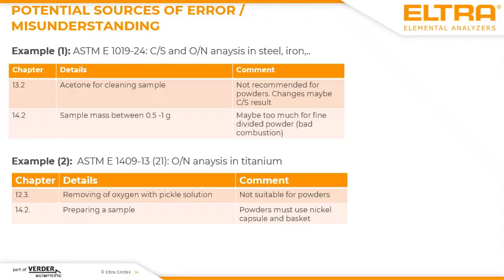And these are, for example, possible conflicts you are facing with your analysis when you are not familiar with powder analysis in the first round. When you have a look at the very prominent standard ASTM E1019, which mainly deals with CS and ON analysis in steel and iron-based samples, you would find just a statement in one chapter that it's okay to clean the sample with acetone. But this is something you should not do when you have a powder-based sample, because then you have maybe some chemical reaction effects or some absorption effects which should be avoided. The other thing is the applicable sample mass. You find in one chapter a statement that you should apply a sample weight between 0.5 and 1 gram. But this sample amount could be too much when you have a very finely divided powder, which is blown inside the furnace.